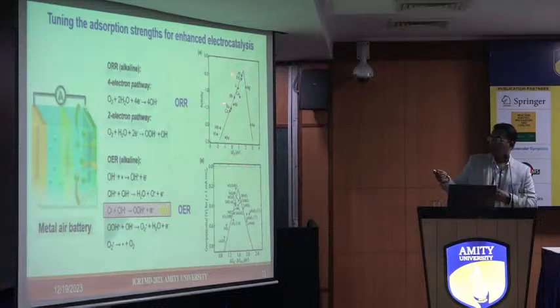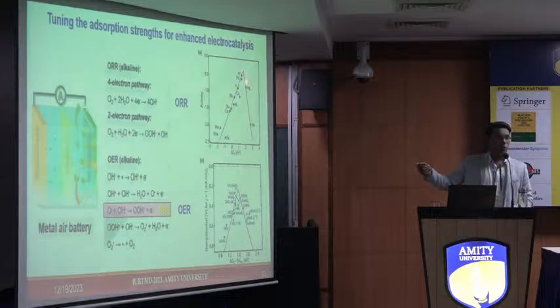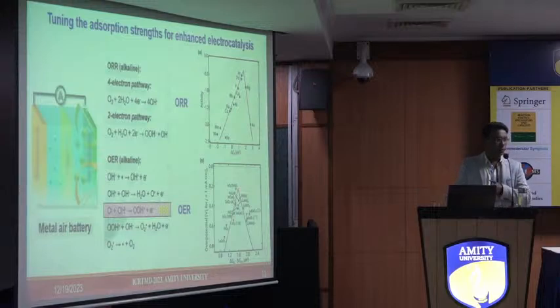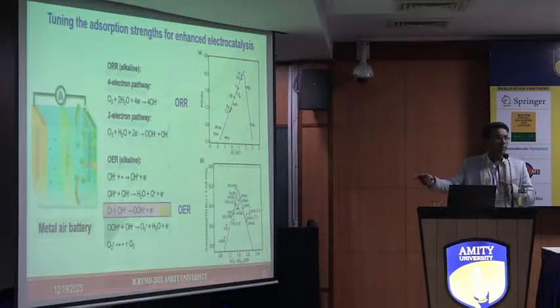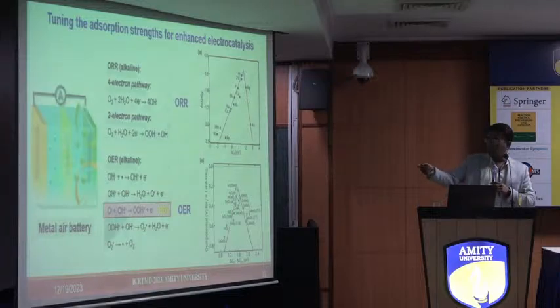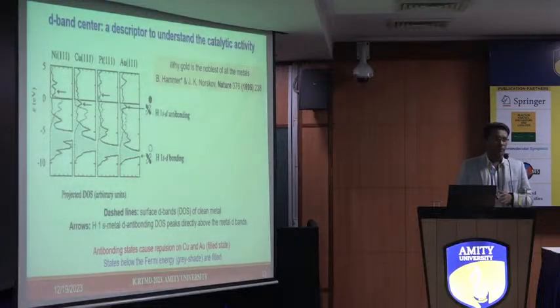Now one important point you can notice here: for the oxygen reduction reaction, platinum is the most active, but if you go to the oxygen evolution reaction, iridium dioxide or ruthenium dioxide is the most active. And platinum is not a good catalyst for the oxygen evolution reaction. So that is the catch. The state of the art materials are not showing bifunctional activity, meaning a single material is not useful for the two applications.